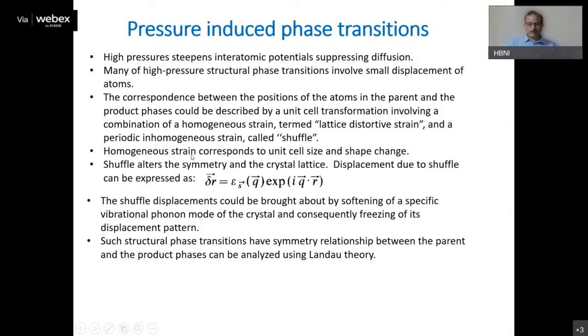If we have a shuffle, we can describe the shuffle as some periodic function, because you have long range ordering in crystals. So the shuffle also should have some periodicity. We can describe this displacement in the case of shuffle as a periodic function where Q is the momentum vector, and that is related to the long range ordering of the system. And this shuffle displacement would be brought about by softening of a specific vibrational mode. Whenever there is a shuffle, there should be some vibrational mode that corresponds to the oscillation of these basis points relative to each other.